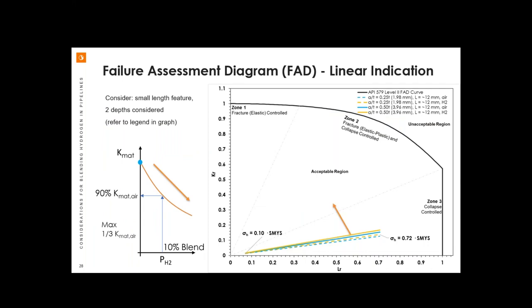So here we see the first 2 features, feature at 25% deep and 50% deep, not very long, less than an inch. And we note that at various stress levels between 10% and 72%, these features, even in air and hydrogen, are quite acceptable. We're in our acceptable region. And the failure mode, had we continued to increase pressure, would be collapse controlled. Here you see the throwback to Christian's section where we note that with a 10% hydrogen blend, we still are able to hold 90% of our original fracture toughness.